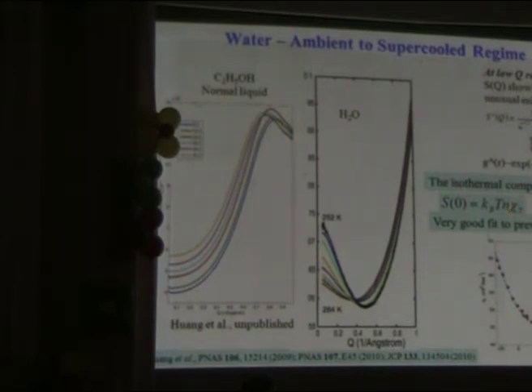This is connected to the isothermal compressibility. And this has been extracted from sound measurements, sound velocity measurements in a liquid. And that's the dashed line. And the red and black curves here is what we extract from the small angle X-ray scattering. So we have a very good fit to that data. We can also, from the anomalous component, extract a correlation length through the Ornstein-Zernike relation. And I will come back to that at the end of the talk, because that was requested before.